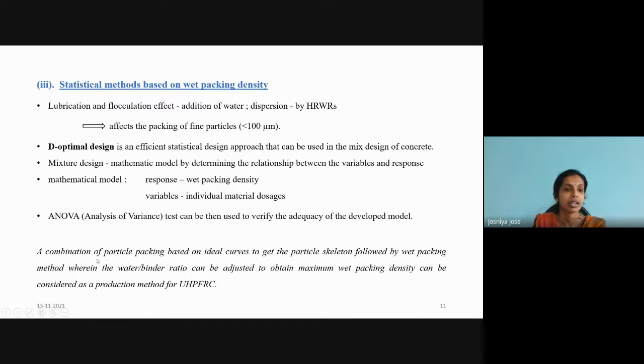So considering all these, it is suggested to use a combination of particle packing based on ideal curves to get the particle skeleton at first, followed by the wet packing method, wherein the water binder ratio can be adjusted, and then obtaining maximum wet packing density. And this method can be considered for the production of an efficient UHP-FRC.